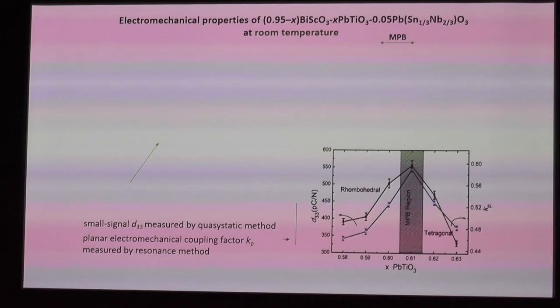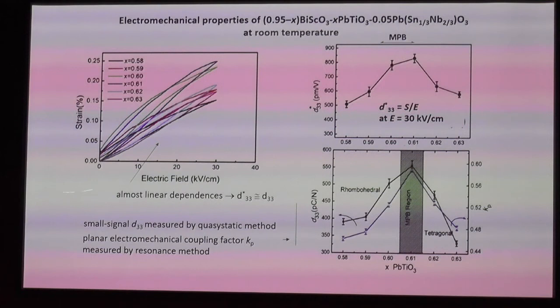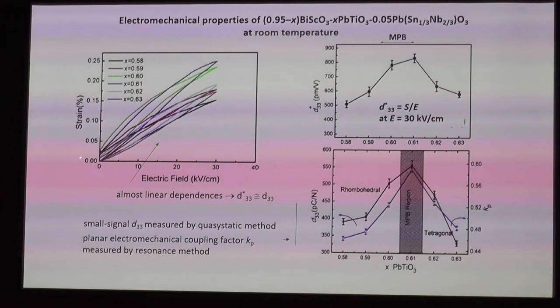And if we measure the strain under unipolar electric field, we observe almost linear dependence of strain on electric field with comparatively small hysteresis. This means that the effective piezoelectric coefficient, which is measured as the strain divided by field, is about the same as the small signal coefficient, a little bit higher, and depends on field.